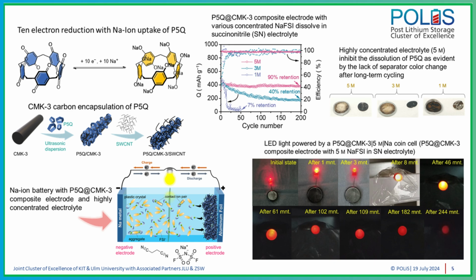Secondly, we have made use of highly concentrated sodium ion electrolyte in order to stop the dissolution of this pillar-5-quinone into our electrolyte. So this dual mitigating strategy helped us to achieve a record cycling stability and improved electrochemical performance both at ambient temperature and at an elevated temperature of around 40 degrees centigrade.